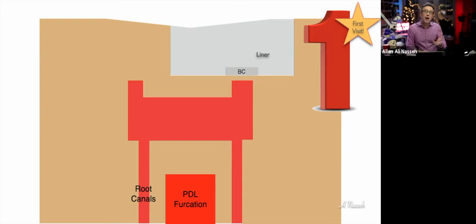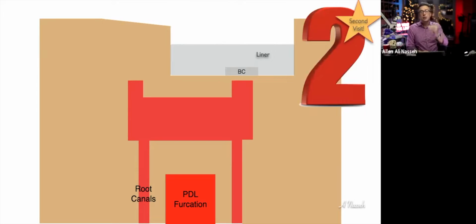If the tooth does well, the pulp remains vital, and you don't need to do root canal therapy. All you need to do is just drill about 2 millimeters into this material and then fill it back up with a bonded composite with a surface that can be polishable and so on, because you don't want to have a resin ionomer facing the surface in the long run. And that would be it.